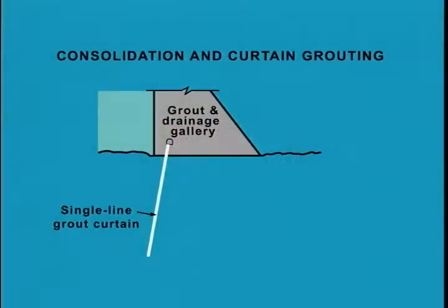The depths of secondary holes will depend on the grout admissions for the adjacent primary holes but will usually be somewhat less. Similar procedures are used for tertiary and quaternary holes. At most rock foundations, the single-line curtain is employed. Where poor rock quality exists, a triple-line curtain is commonly used to reduce erosion and piping potential. Upon occasion, a five-line or seven-line curtain has been constructed, with the final two lines of micro-fine cement or hard, durable chemical grout after setting.